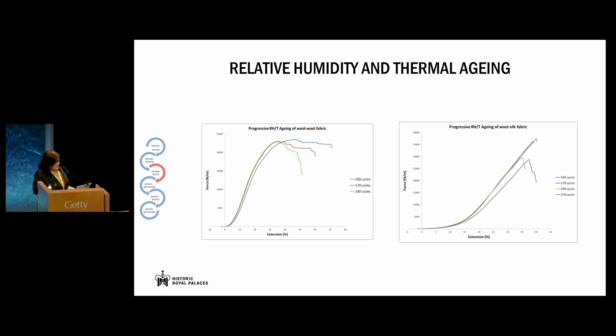So let's proceed to the results. The figure on the left shows the tensile testing results of wool weft fabric after 100, 170 and 240 cycles, showing that the higher the number of cycles, the higher the loss in fabric strength and extensibility. The stiffness of the fabric also increased, as indicated by the increase in gradient in the elastic region of the graph. The results, however, of the silk weft samples on the right indicate that the effect of RH aging was slower, with a first significant decrease in strength observed in 240 cycles.